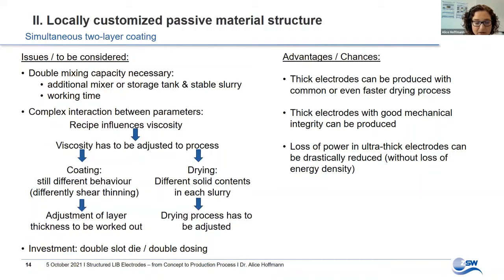The investment of a double slot die and double dosing is comparably small. And the advantages are that by this method, very thick electrodes with good mechanical integrity can be produced with a common or even faster drying process. Furthermore, the loss of power accompanied by ultra-thick electrodes can be drastically reduced without a loss of energy density.